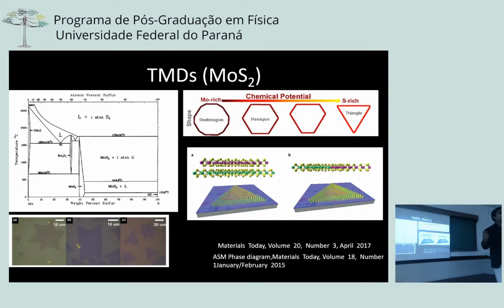Moving ahead with these 2D materials, the next generation which came in 2011 was transition metal dichalcogenides. What it means? You have a transition metal, moly, and a chalcogen family member, sulfur. MoS2, WS2 became very popular. Compared to graphene, one of the interesting aspects in these TMDCs was they have two elements, right? So it's not just carbon alone, you have moly and sulfur. Another interesting aspect was, if you look at the phase diagram with temperature and composition, MoS2 exists in this phase range.